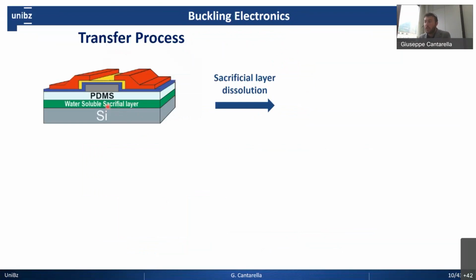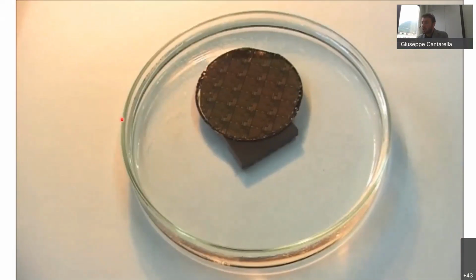We used a silicon carrier wafer coated with a sacrificial layer. This is what you see in green. This is a water-soluble sacrificial layer. Then we use our rubber, our stretchable substrate, and then we complete the electronics fabrication. Afterwards, when the fabrication is complete, we dissolve the sacrificial layer to detach the PDMS from the carrier. This is exactly what you see in this video.